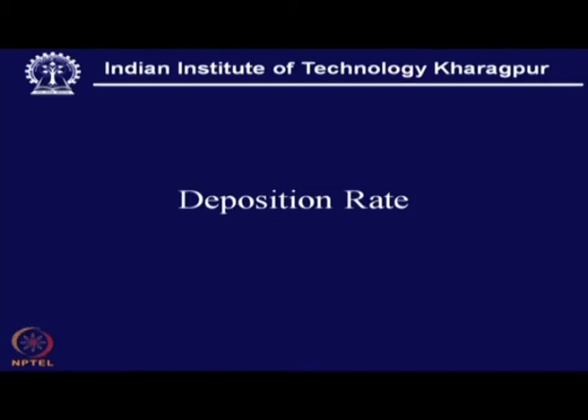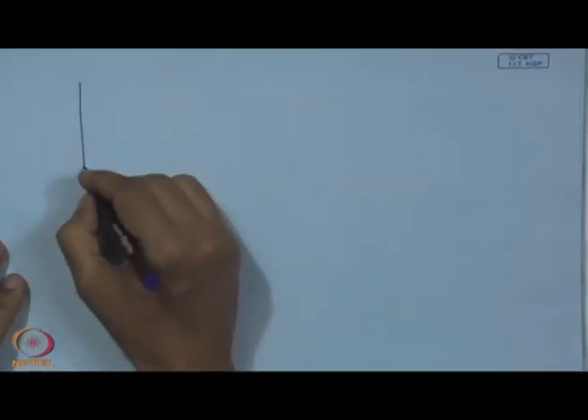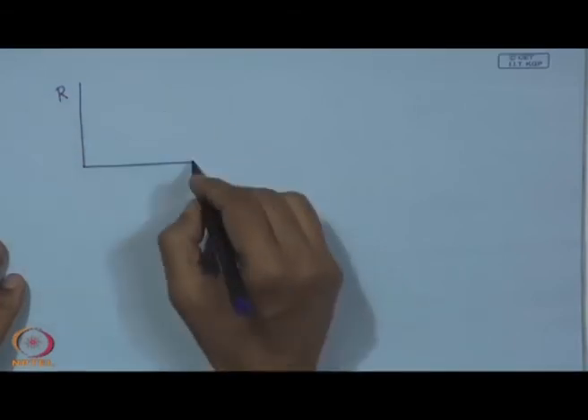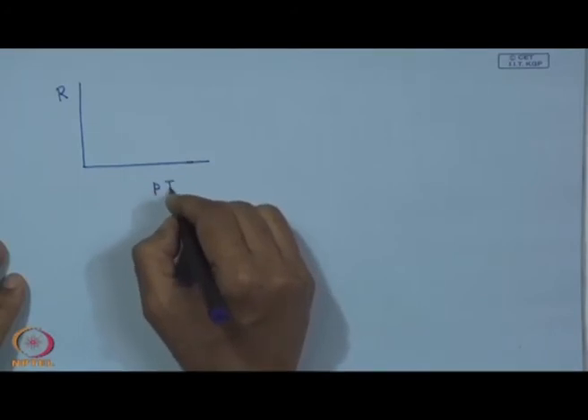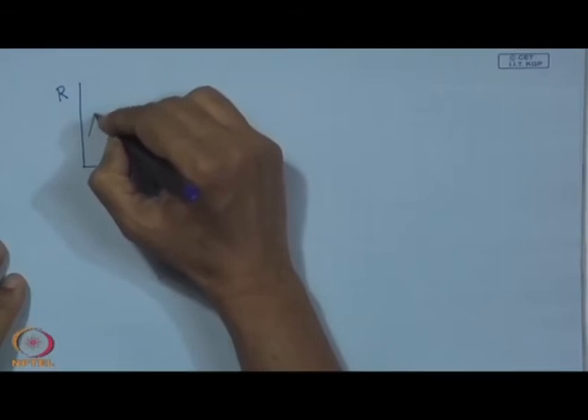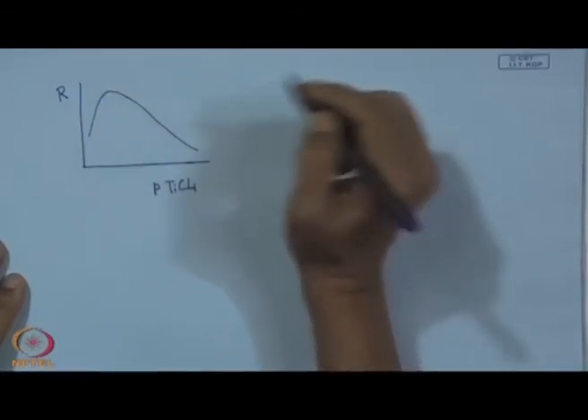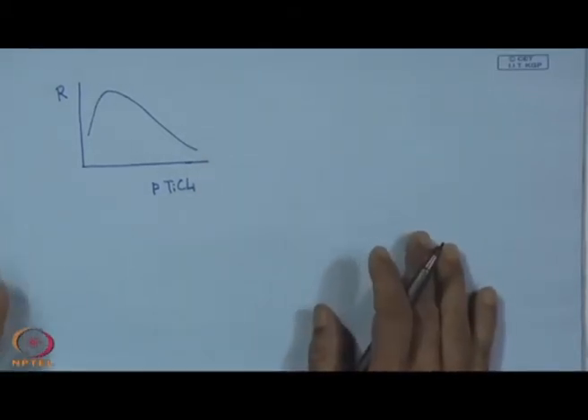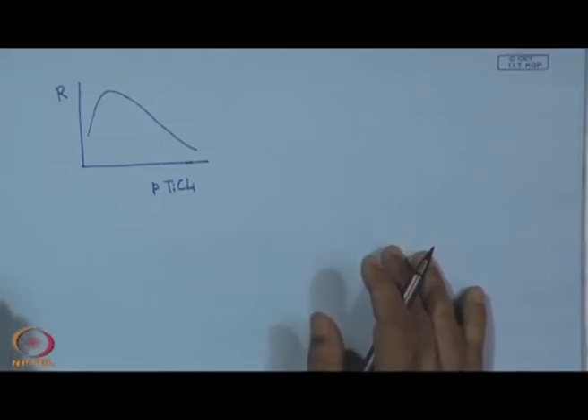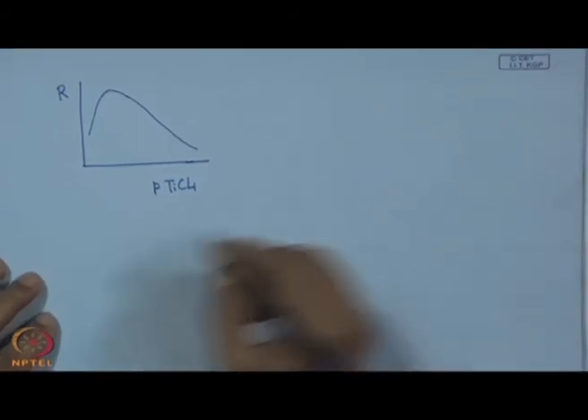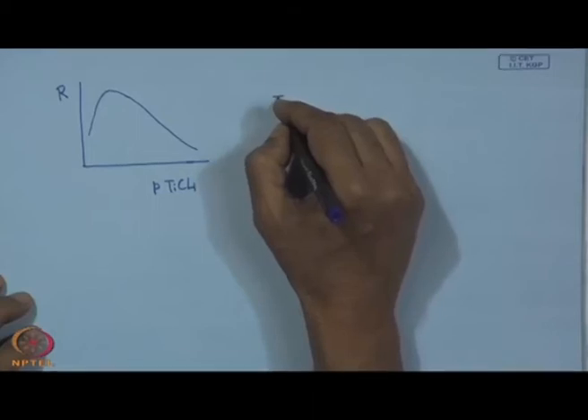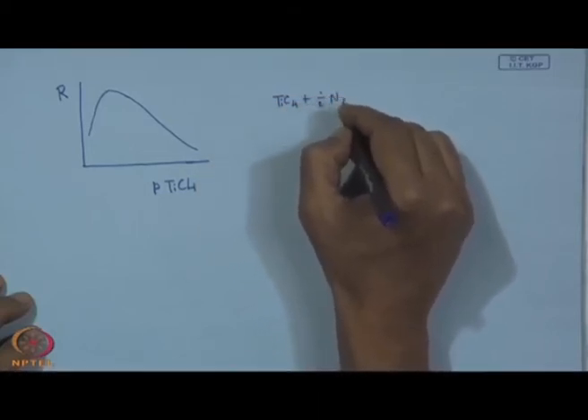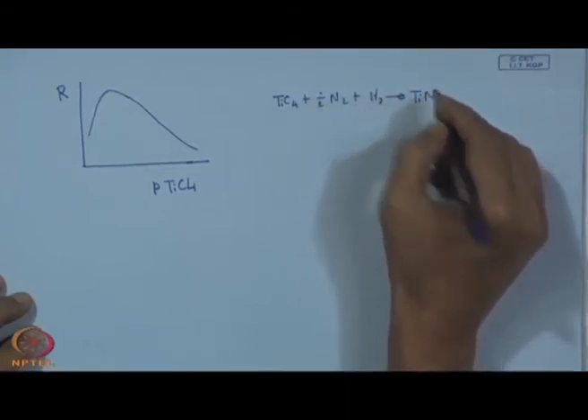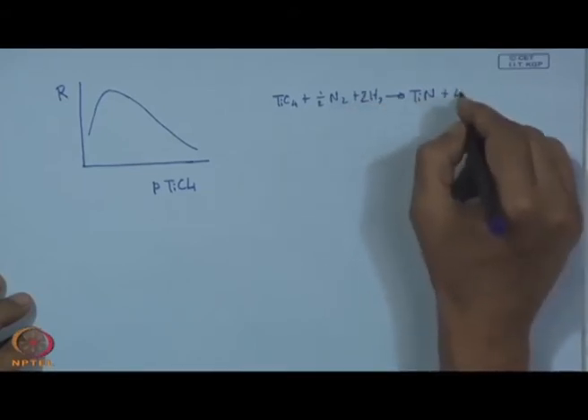So, one would be interested to know what is the deposition rate. So, if this is the deposition rate and this is the concentration or partial pressure of TiCl4, it comes like this and it falls drastically. What does it mean? That means for a given condition, if one keeps on increasing titanium tetrachloride, then it is found that the deposition rate starts falling and almost comes to 0. This is because one can look into this reaction, that means here TiCl4 plus half N2 plus 2H2. So, for one molecule of TiN, what do we get? We get actually 4HCl.